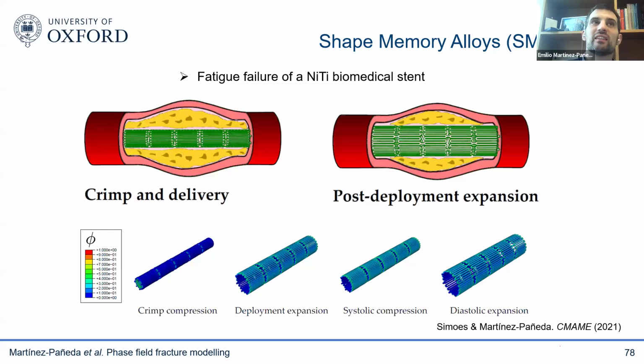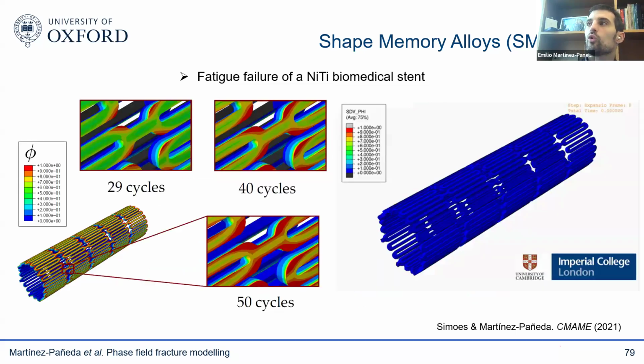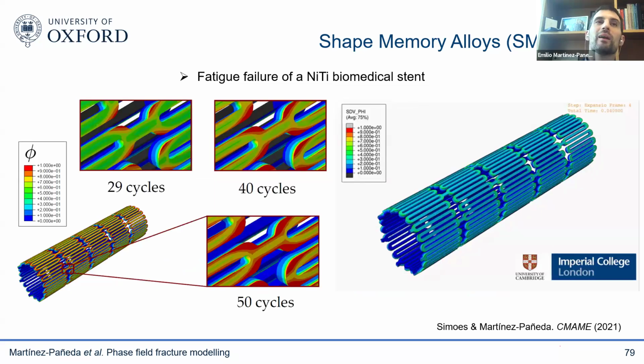And one application that we were very interested in is biomedical stents. These materials are widely used by the medical community because when you have a stent, basically what you want is, you have a clot, you have something blocking blood flow. So you want to again enable the blood to go along your body, along your veins. And the way to do that is to bring one of those stents, and then you need something that can change shape quite significantly without deforming irreversibly. So the superelasticity capabilities of these nitinol alloys are very convenient, because then you basically compress it, you put it into your body, then it expands, and then it will undergo many cycles of compression and expansion as your heart keeps providing blood to your body. So then the main issue, of course, here is fatigue. You want to make sure that you have something that doesn't get damaged due to fatigue because it'll undergo many, many cycles in your body.